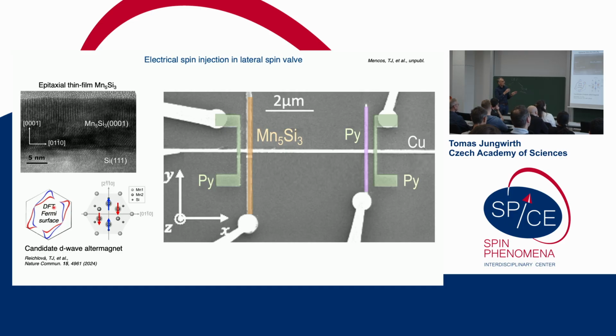But when people are trying to study spin transport experimentally, they like to disentangle spin injection from spin transport and from the detection of the spin. And for this, they use this lateral spin valve device, in which what you see is an injection electrode. Then there is a channel through which the spins can transport the spin information, and then there is this detection electrode here. And as you see from the scale here, the injection and detection electrodes can be separated by hundreds of nanometers. So we talk about a non-local spin device or non-local spin detection.